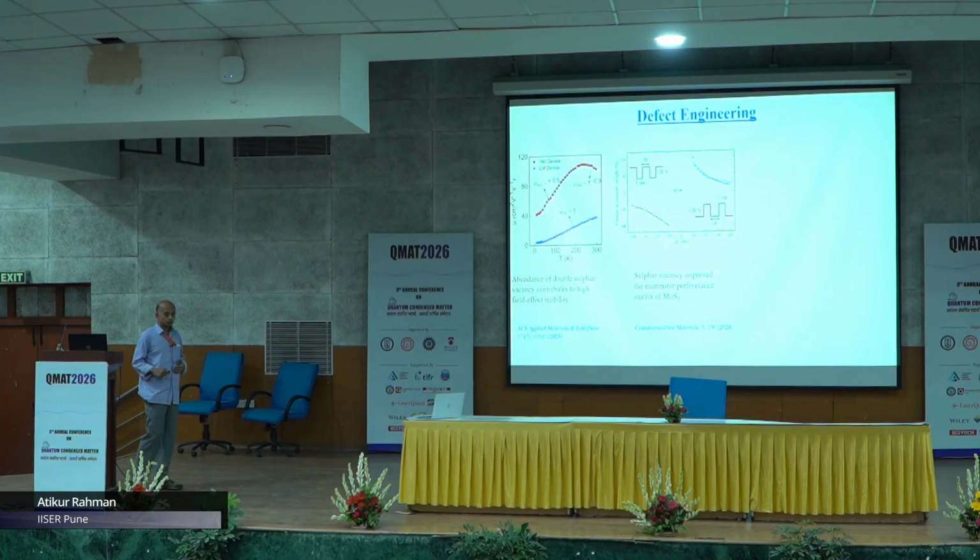In another work, we showed that by using a low power argon plasma, you can create sulfur vacancies, and those samples are good for memristor applications. The memristor performance improves significantly.